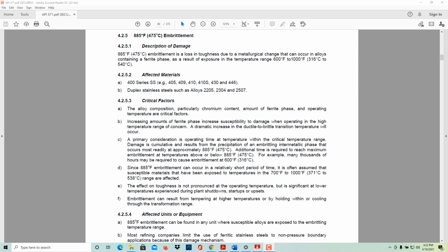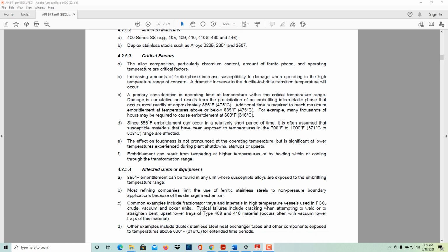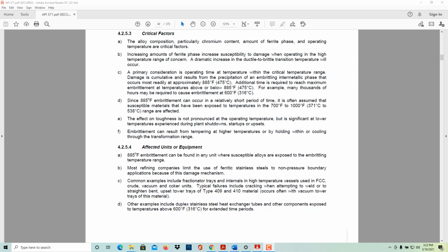Critical factors. The alloy composition, particularly chromium content, amount of ferrite phase, and operating temperatures are critical factors. Increasing amounts of ferrite phase increase susceptibility to damage when operating in a high temperature range of concern. A dramatic increase in the ductile to brittle transition temperature will occur. A primary consideration is operating within the critical temperature range.